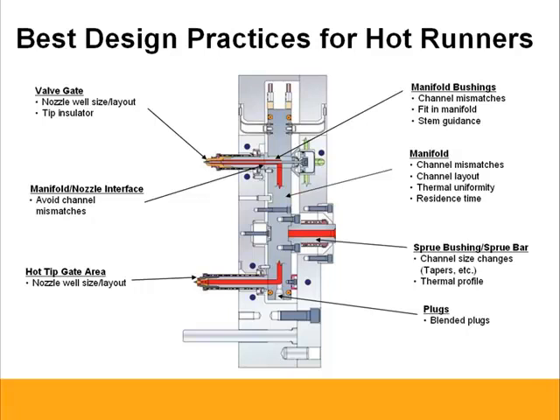The channel layout itself should be optimized for color change, and a good balance between pressure drop and shear rate, and thermal uniformity, of course. The sprue bushing should be the same size from an orifice point of view as your machine nozzle, and I will show you the example in just a second why that actually matters.